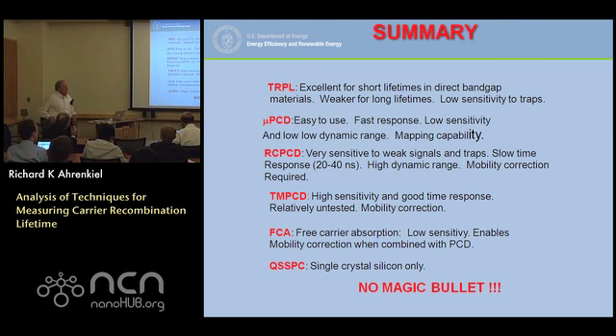Yeah, I think that was the point of this, that you get all these different shapes. And the shapes can originate from different internal sources. I neglected one of the biggest shape changers that we see, and this is in silicon where you have deep level defects, and you can fill those at higher injection, and then you get a convex decay curve rather than a concave decay curve. And we see this a lot. What happens is at high injection with the deep level defect, you'll start out with a high lifetime, it'll drift over to a low lifetime.